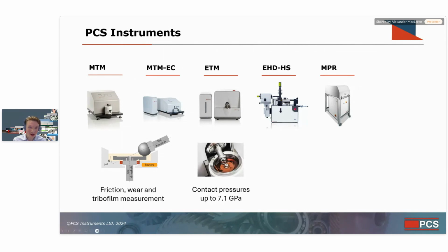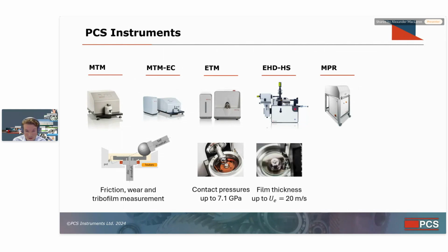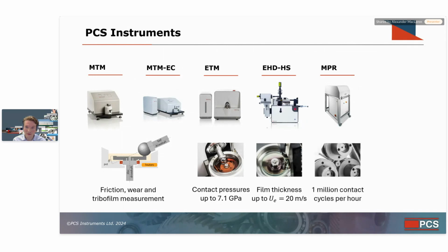Its younger brother, younger but much stronger brother, the ETM or extreme traction machine, which Amir mentioned briefly, can achieve contact pressures up to 7.1 gigapascals, obviously material dependent, in a circular contact. And it's the only machine that can achieve these pressures currently on the market. And so that's really good for understanding how lubricants behave under those conditions. The EHD high speed can achieve entrainment speeds of up to 20 meters a second, and similarly is able to measure film thickness in this quite extreme condition. And Amir showed some of my work during my PhD showing how strangely films can behave at high speeds as a result of the thermal coupling.